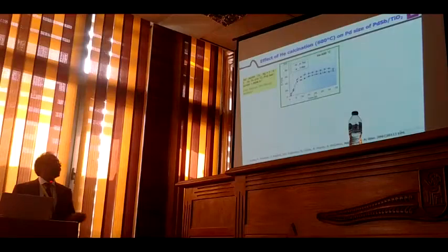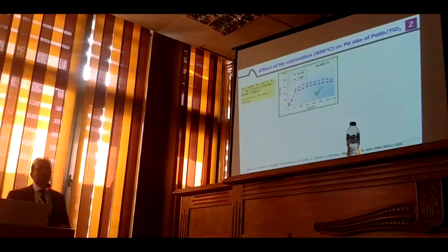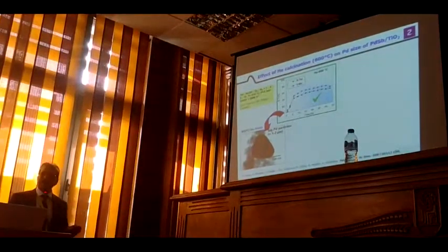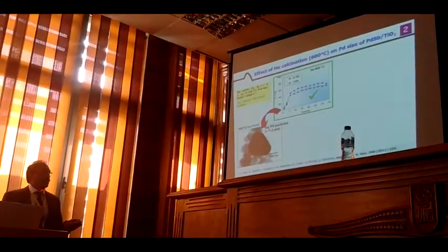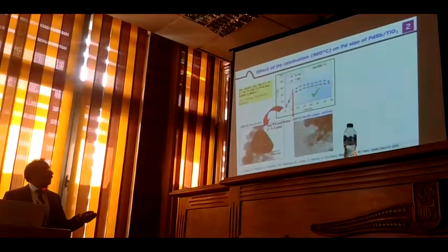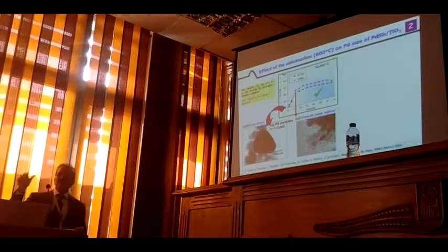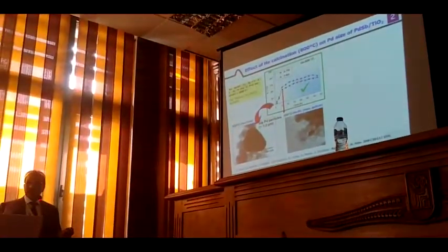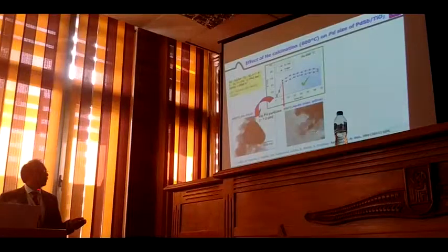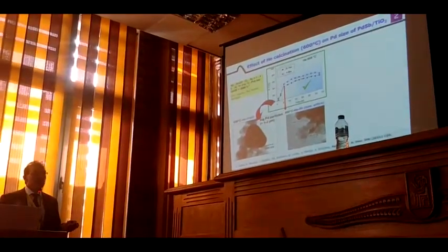So then let's compare with the helium one. When you calcine in helium, the long-term stability is much more improved. The induction period remains the same as the air one at 600, but somewhat better than the first one. So on the whole, helium is the best. Again, if you look at the particle size, when we calcine the catalyst in helium at 600 degrees centigrade, we have seen the formation of the biggest particles, too much, huge. Quite a surprising thing is that these bigger particles undergo a kind of reconstruction or tuning itself under the influence of reaction conditions and the reactant feed mixture, and it forms again particles of the critical size of 30 to 50 nanometers, which is really surprising.